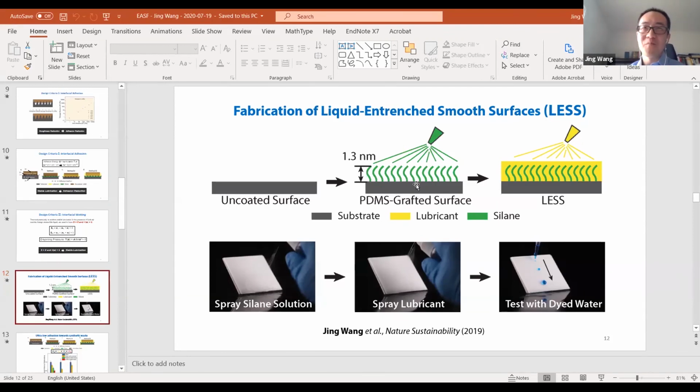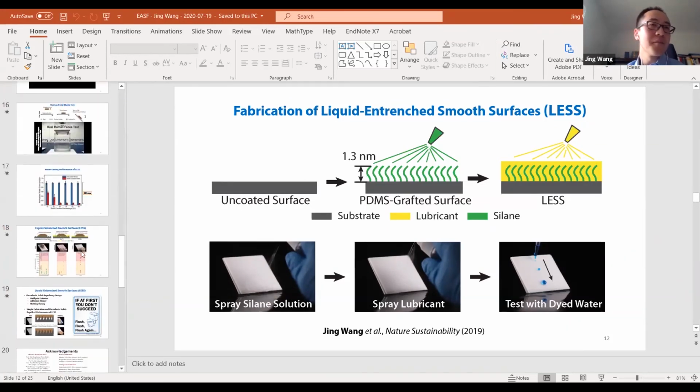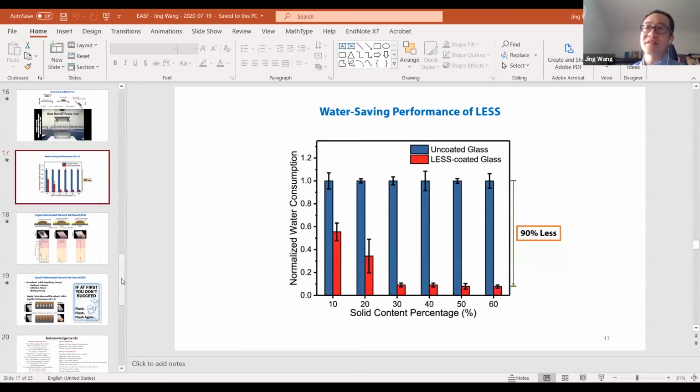Yes. We tested this: when we do the water consumption measurements here, what we see is that when we impact the fecal waste, it generally slides off or bounces off our coating. And when it attaches, the flow moves it very easily with minimal shear.